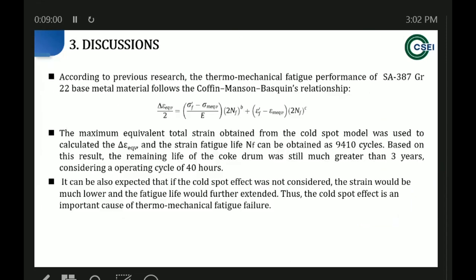And so from the above results, we can discuss two things. One is, according to the results we simulated, we can use the Coffin-Manson relationship to calculate the fatigue life of this coke drum, and we obtained 9,400 cycles of life, and this is greater than 3 years. And so that does indicate the cold spot effect is important to cause the thermomechanical fatigue failure.